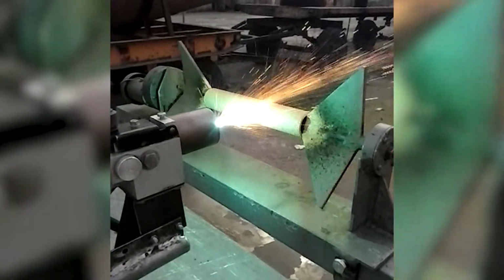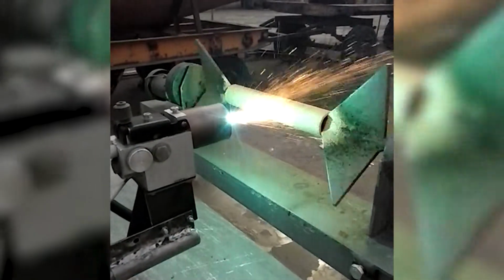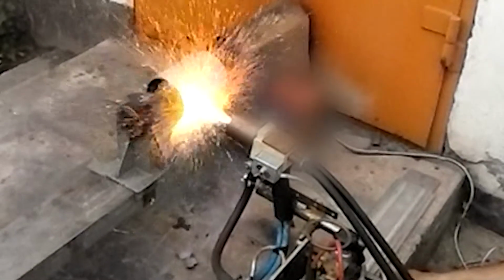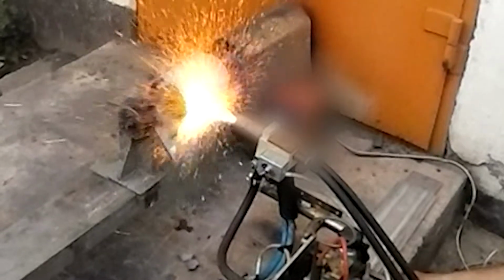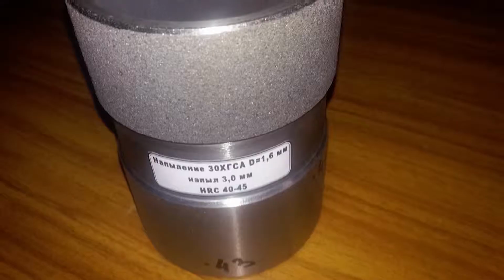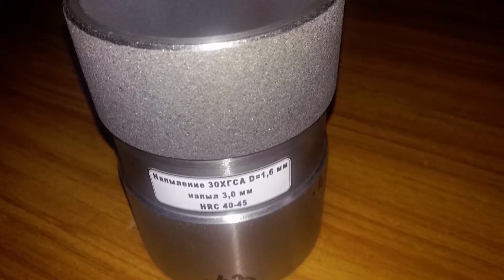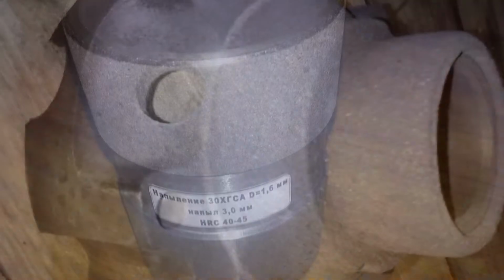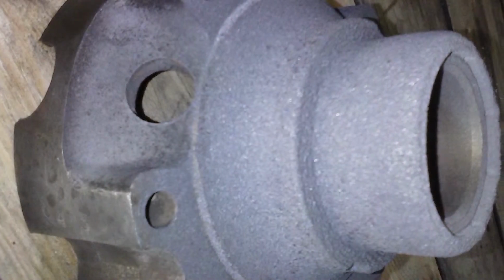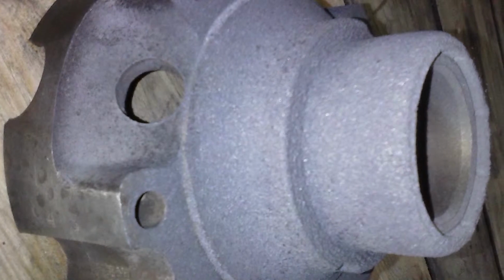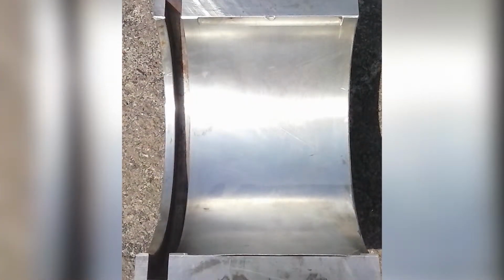Due to the combination of high temperature and high speed of drops, the covering turns out with special properties, with high coupling strength and low porosity. The electric arc furnace metallization is a cold process of thermal spraying whereby the temperature of the detail surface does not exceed 150 degrees Celsius. It excludes changes in the structure of the metal or deformation.